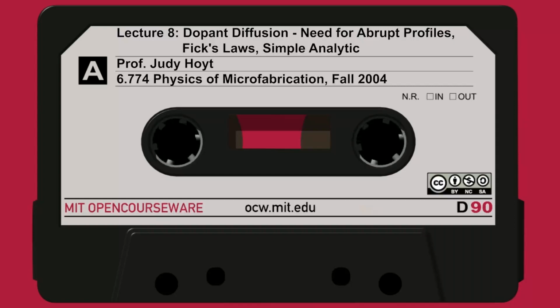Let's go on to slide number 35 and talk a little bit about the dopant diffusion coefficients themselves. We're just going to talk first about what we call intrinsic dopant diffusion, which happens when the dopant concentration is less than n sub i, so the semiconductor is considered to be intrinsic. Generally, we can write these intrinsic diffusion coefficients in an Arrhenius type relationship, where the diffusion coefficient is just some constant D naught times exponential of minus E_A over kT.